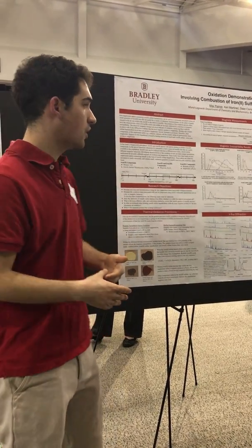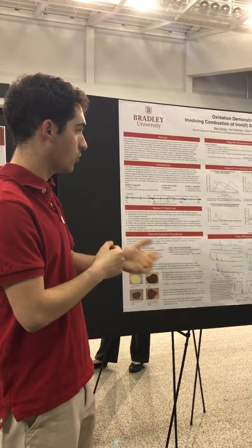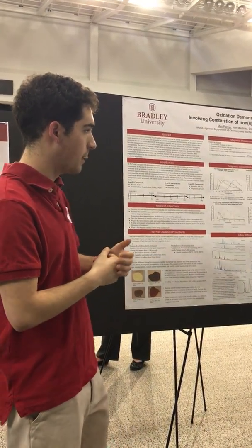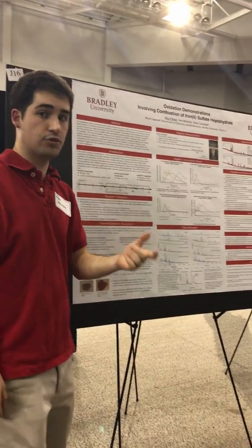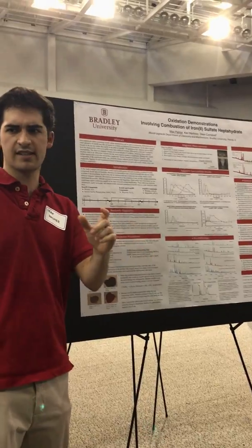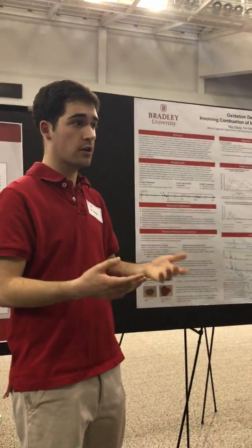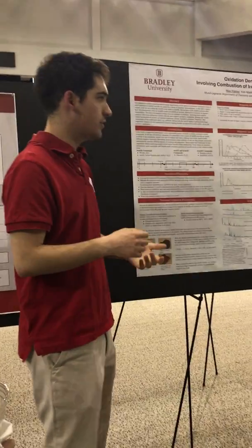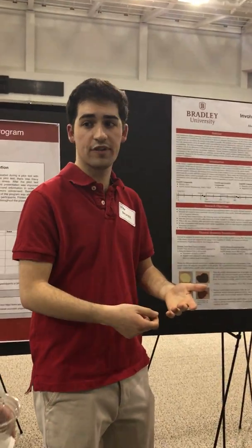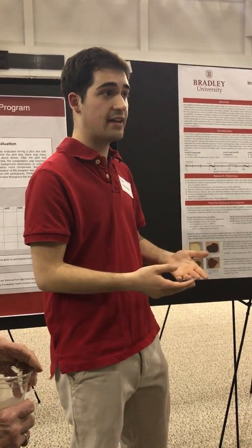So here we have the tablets and we can see that they are a lot more magnetic than just the iron 2 sulfate. And whatever isn't iron 2 sulfate in the tablet, it's a cellulose gel, and cellulose is very similar to starch, or potato starch. So then we mixed just the iron 2 sulfate with potato starch, and we ran that as a trial.